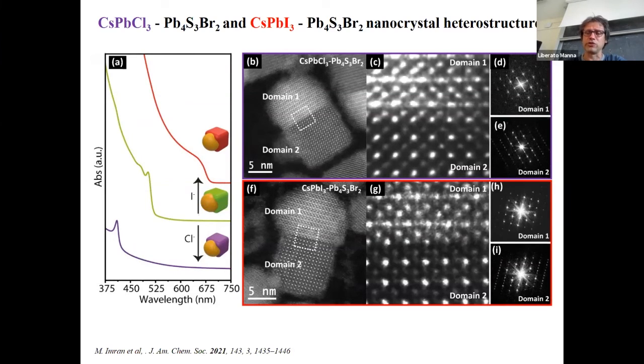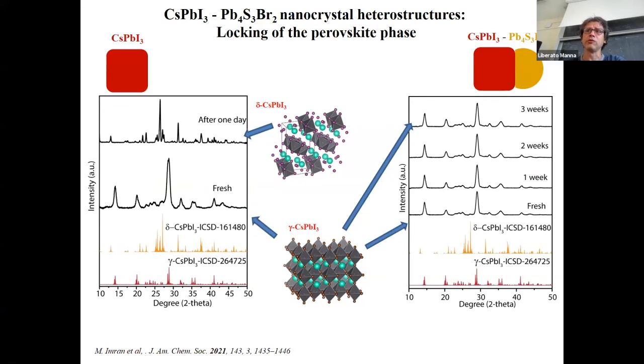And again, there is a quenching of the PL. Now, what can you do with this heterostructure? Well, if you synthesize cesium lead iodide, this grows in the orthorhombic gamma phase, but this phase is very unstable at room temperature. So if you make just isolated nanocrystals of this perovskite material, basically in a few days it will transition into this non-perovskite phase made by one-dimensional chains of edge sharing octahedra.